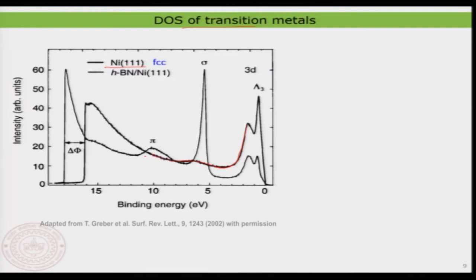But what is quite striking here, again in binding energy, and this zero would therefore represent the Fermi level, is that the density near the Fermi energy is no longer looking like a normal flat function as you have seen in the case of gold. Instead, it is looking much more spiky like this. This is quite interesting, because the nature of this density of state near the Fermi energy would decide how reactive a material is.